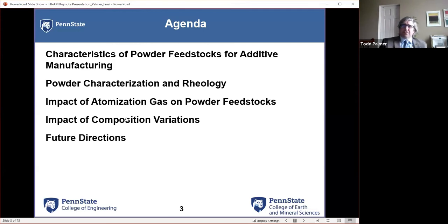And then I'm going to talk a little bit about composition variations. And when I talk about composition variations, I'm talking about something that will meet a current specification for the material. So if you go into the ASTM standards for a nickel chrome moly alloy, this alloy will fall within those specifications. But what we're going to see is if we take one or two alloying elements and move them from minimum to maximum areas, and most specifications were written by people who make the materials. At first glance, we will say to ourselves, well, of course, those are the people who know how to do it. The opposite side of that coin is that they're going to try to make the specifications and the standards as wide as possible so they can sell you product more easily and more inexpensively. So the minute specifications get tightened up, the cost of the product goes up. So, or at least to make it, they can still sell it to you at a premium. But these compositional variations are going to impact that.